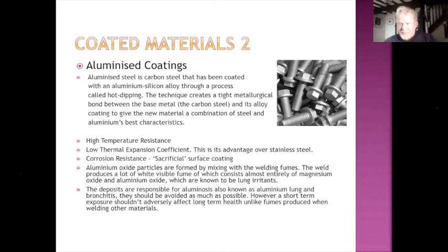Typical application of an aluminized coating now is on exhausts. So if a bracket breaks off and you need to put that bracket on, clean the area where you're going to put in that weld. And again, work on those sorts of margins of clearance. You can get a cold aluminized paint that you can put on after the repair has been carried out, to ensure that you get back that corrosion resistance. But with any aluminized coatings, when you start to heat up, if it's not running properly, the tendency could well be that it is the aluminized coating.